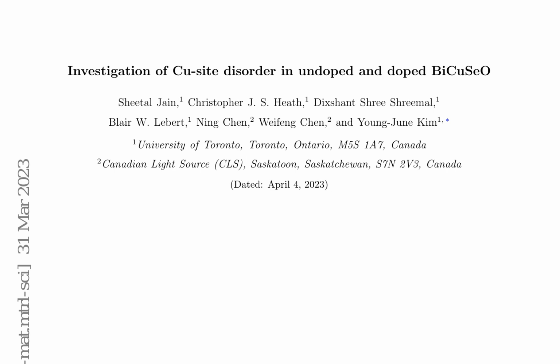At least 3 scans were taken at each edge for each sample to guarantee data reproducibility and good signal-to-noise ratio. EXAFS data processing and fitting were done using the Athena and Artemis software of the Demeter suite, respectively. In data processing, EXAFS data obtained in energy space was reduced using standard procedures, and the resulting K-space data was Fourier transformed, FT, to R space, yielding peaks that correspond to different shells of neighboring atoms.